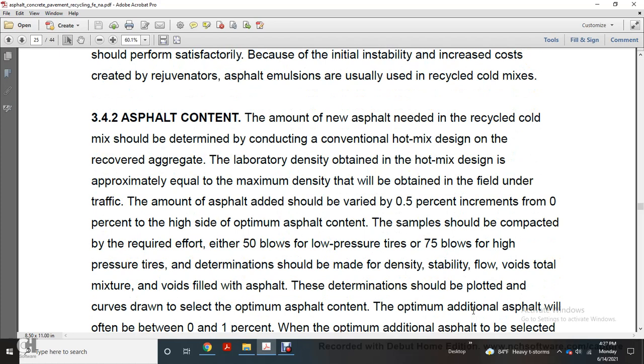Asphalt content. The amount of new asphalt needed in the recycled cold mix is able to be determined by conducting the conventional hot mix design. The density of the recovered aggregate in the laboratory may be obtained with the hot mix design, approximately equal to the maximum density obtained in the field under traffic. The amount of asphalt added should be varied in 0.5% increments from 0%.